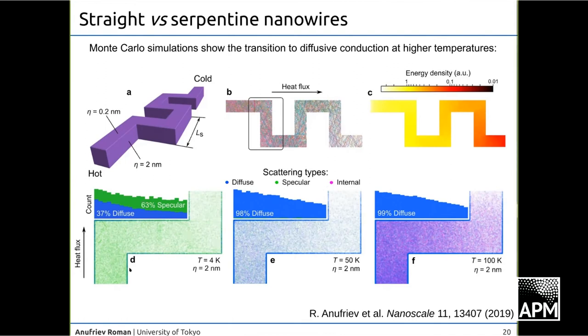We can see that at 4K, everything is green, which means all the scattering is specular, except in the corner, where the scattering tends to be diffusive even at 4K. So the corners really count. But as we increase the temperature, the picture becomes more bluish, more diffusive, and less green. And finally, as we keep increasing the temperature, the simulation shows us that internal scattering starts to dominate heat conduction above 100K. That is why temperature kills ballistic conduction so quickly, and we see it most efficiently at low temperature.